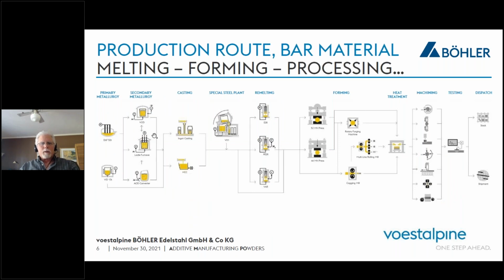Here is a complete schematic of Böhler's bar production route. Nickel alloys are melted in a special steel plant here with a VIM and either VAR, ESR, or PESR. The nickel alloys actually just get VIM or VAR or ESR. And then they're hot worked through either forging or rolling operations, and then heat treatment. Then on to machining. The machining is used to produce a bright surface finish and material that's free from any surface defects or contamination. And then finally, they undergo metallurgical testing and quality inspections before shipment.